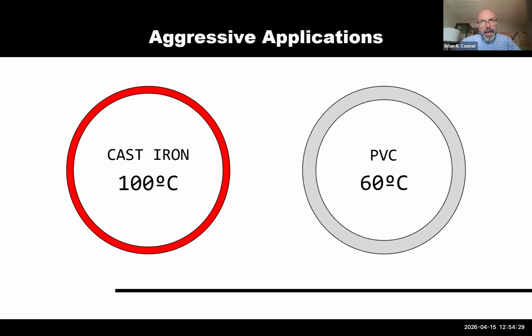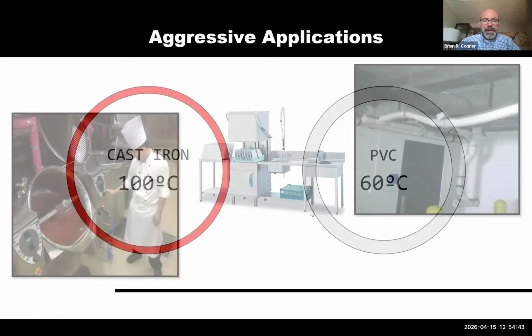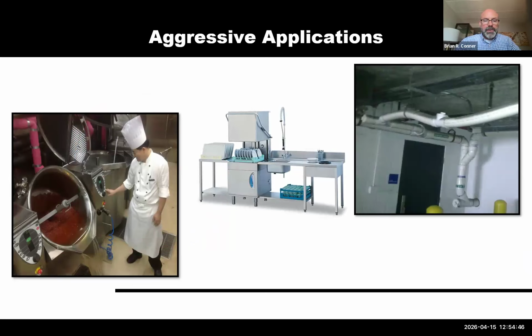Another reason why you may choose to go with iron over plastic pipe is that PVC and ABS pipe have a maximum working temperature of 60 degrees Celsius, where iron can handle 100. And this is especially critical if you start thinking about some of these aggressive applications like commercial kitchens. If you have dump pots for pasta, you're going to exceed the working capabilities. And even if it's dumping at, say, 130 degrees from a dishwasher, even at those high temperatures, the